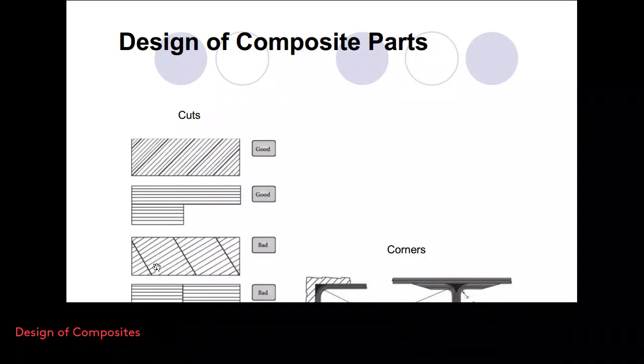So these are the orientations of the fibers, and as you see, these dark black lines are the places of the cuts. So what is the disadvantage? Why is this geometry bad and why is this better or good, in other words? Now we mainly infiltrate the spaces with the matrix material, and this basically means that the fibers have a certain length shortened. In fact, the ends of the fiber do not carry load or much load. So placement of the fabric like this means that you decrease the load bearing capability of the structure.